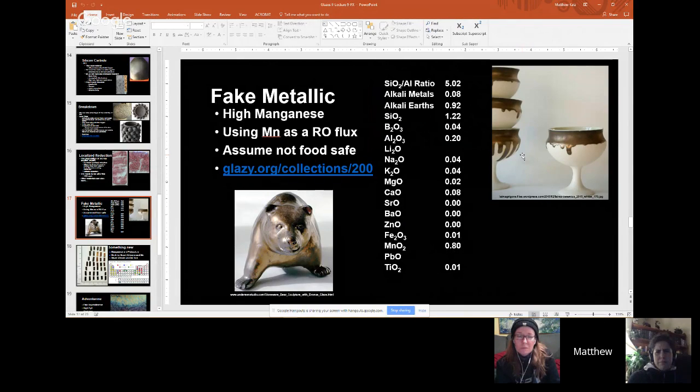You're just crystallizing out manganese crystals, manganese silica crystals, in a glassy base, which look metallic. This can run and this can have a shine and this can be crystallized because it's a matte glaze. These trends are exactly the same. You're just screwing around with your flux ratios and overloading the system with manganese. It's pretty cool at the end of the day.